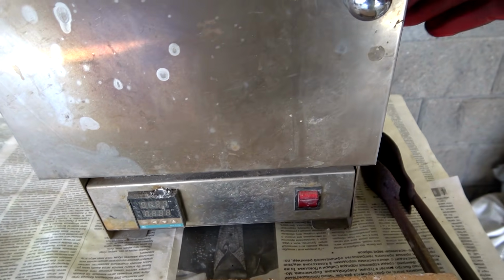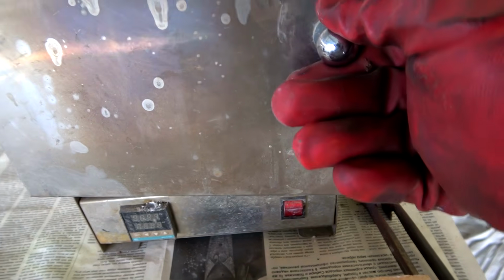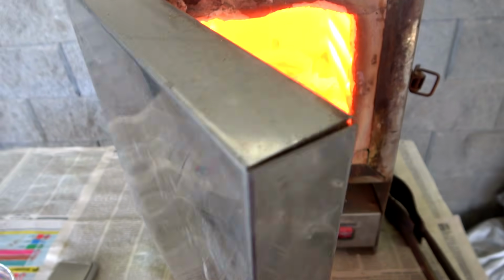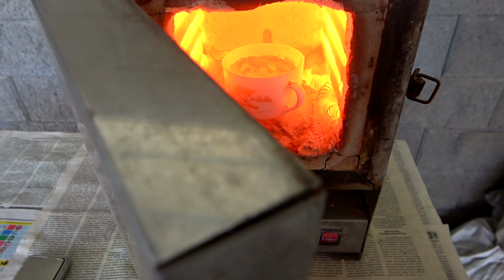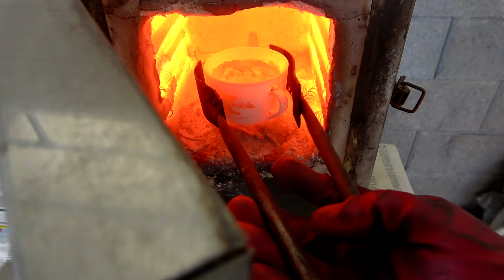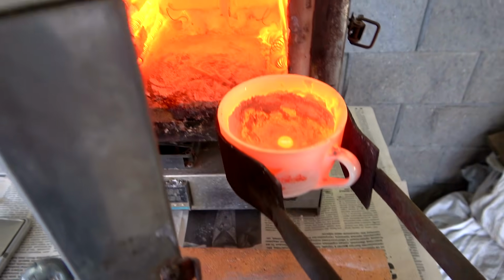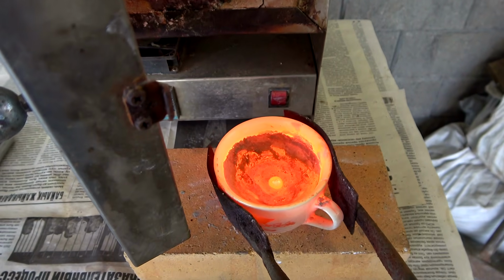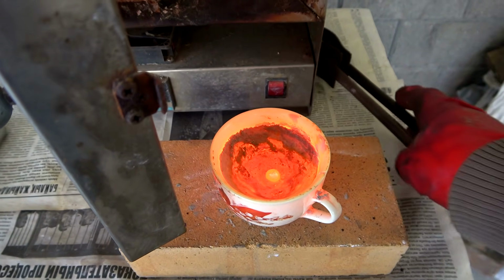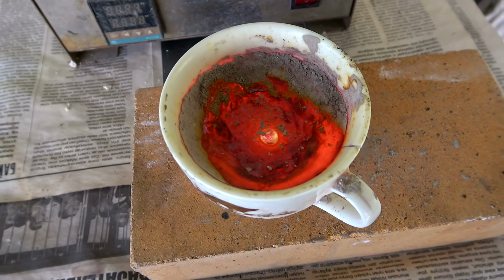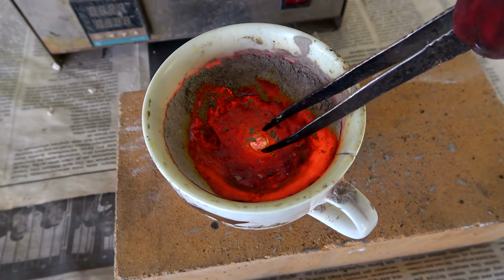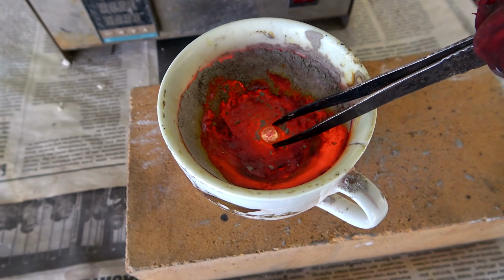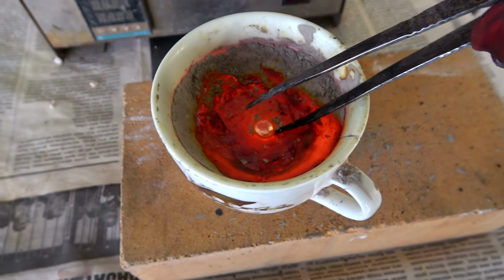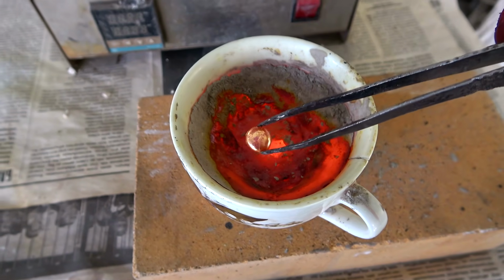After 20 minutes, the process was completed, all the lead evaporated, and now I take out the cupel, and the gold remains fused into a ball. Its purity is not the highest grade. In my case it almost always turns out to be 800 to 850 fineness, in this range. While the cupel is hot, I try to take out the piece of gold in time, otherwise it will be more difficult to do after cooling.